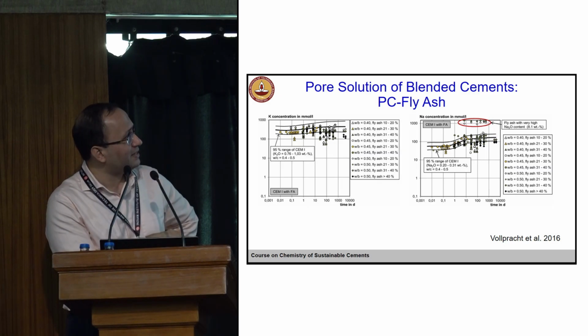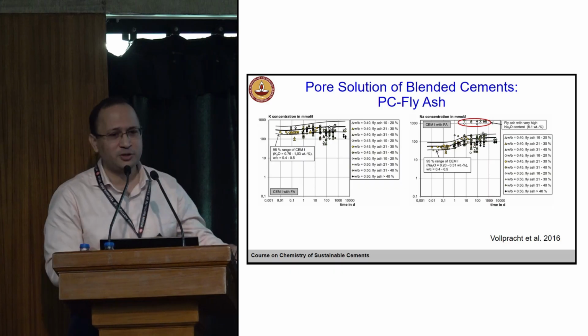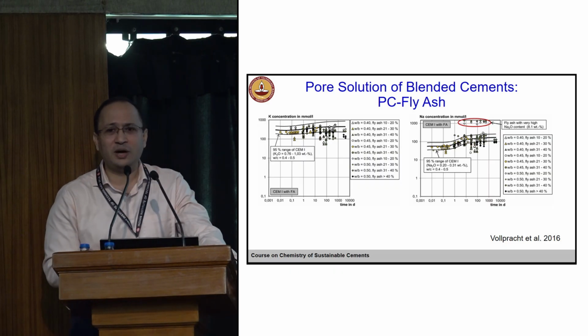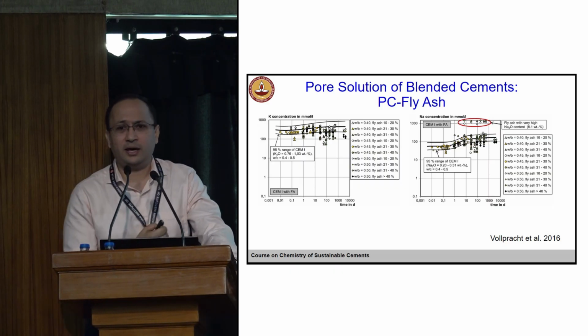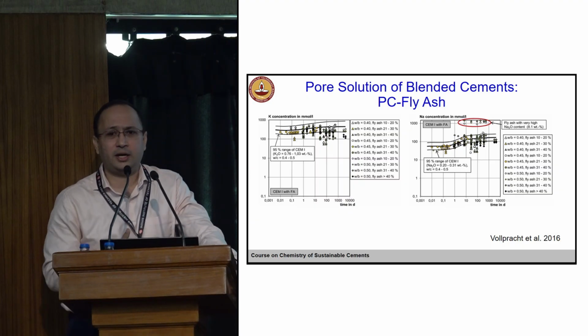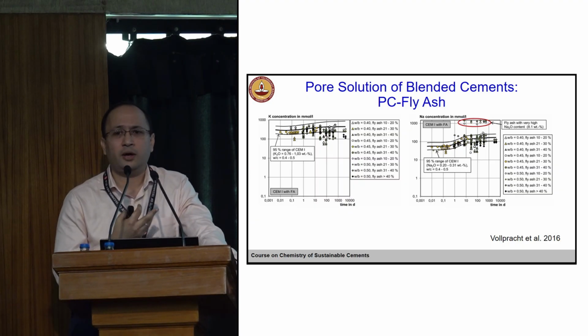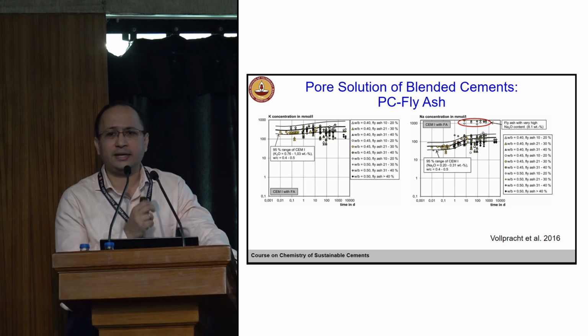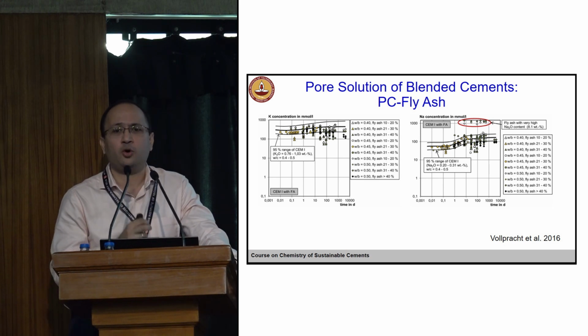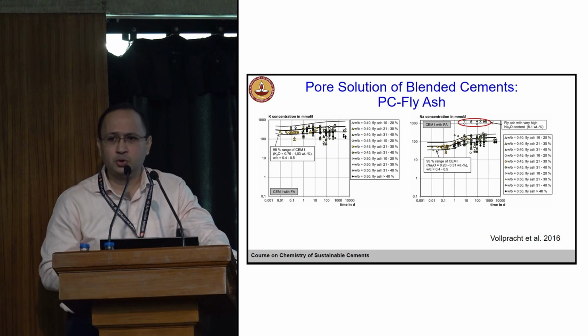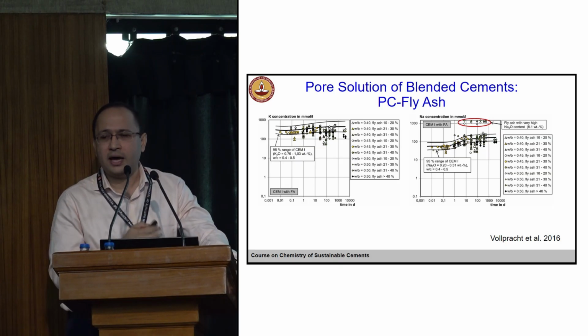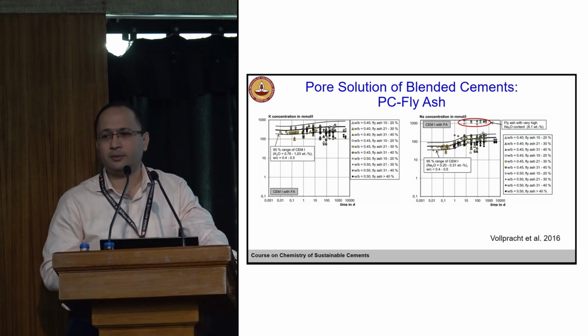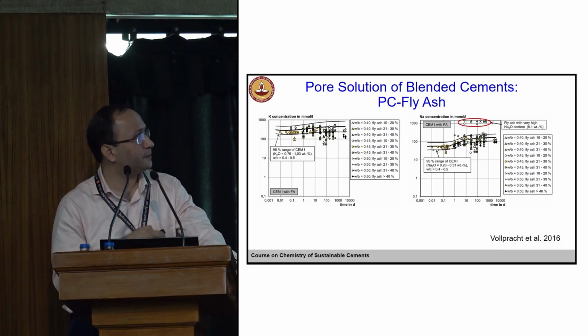You can see a similar thing here, though maybe because there are a lot of data points you are not able to see it clearly, but this is well established, and this can be easily monitored. You can either measure the pH, or you can extract the pore solution and determine the concentration of potassium and sodium in the solution, and that will tell you how the pore solution composition is changing.